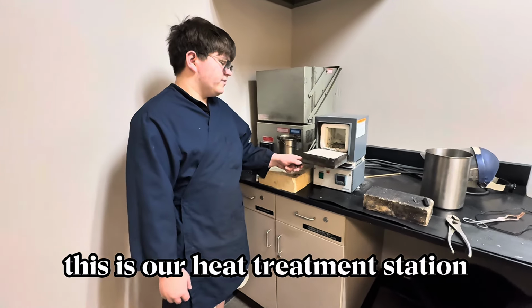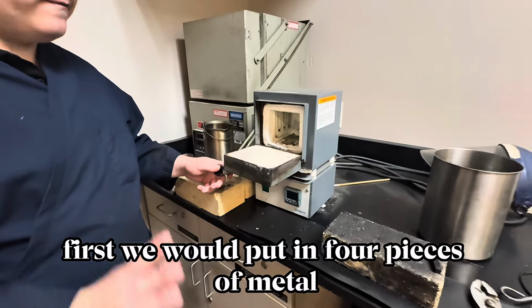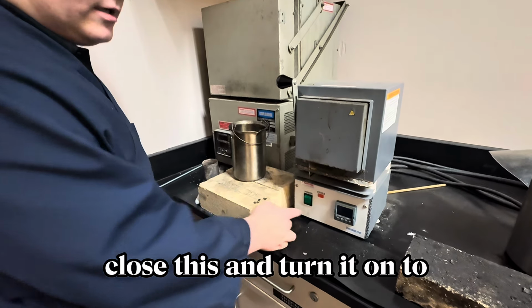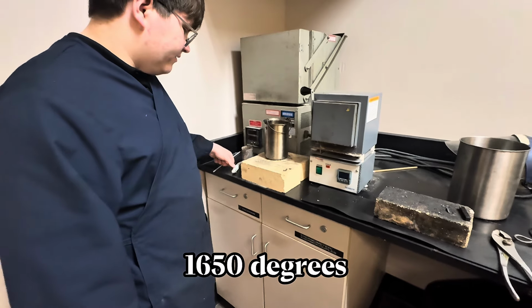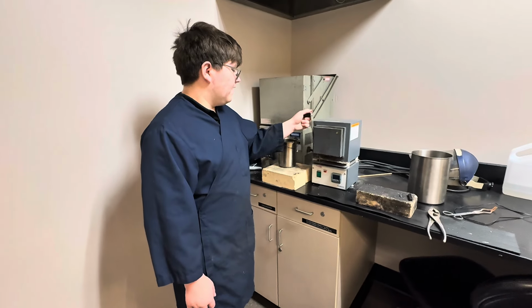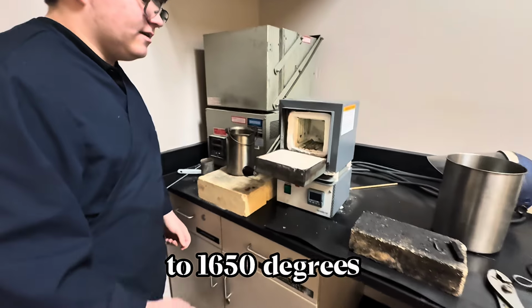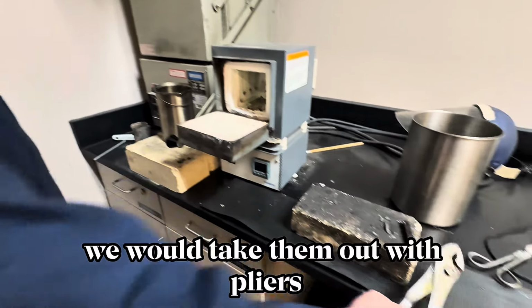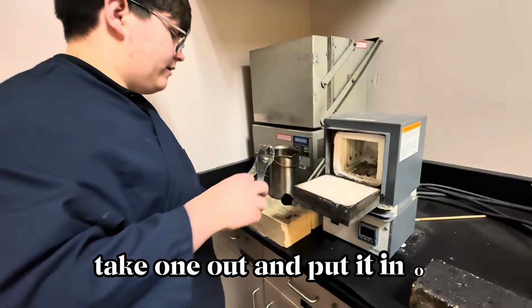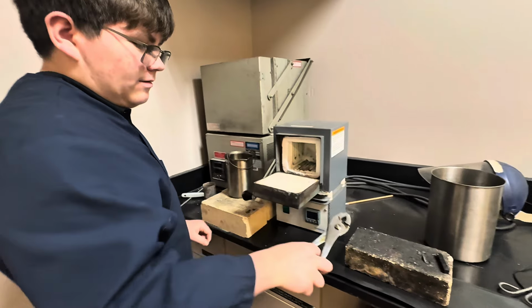This is our heat treatment station. First, we would put in 4 pieces of metal, close this, and turn it on to 1650 degrees. After the pieces are fully heated to 1650 degrees, we would take them out with pliers, take one out and put it in oil, and then put it on the brick.